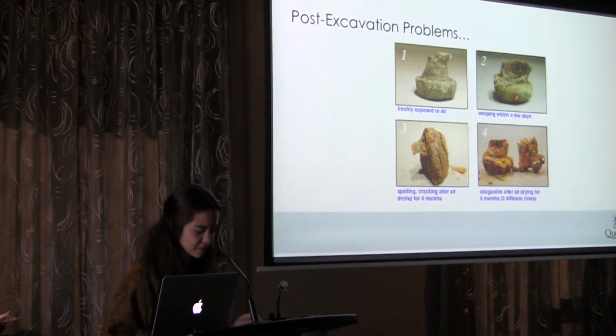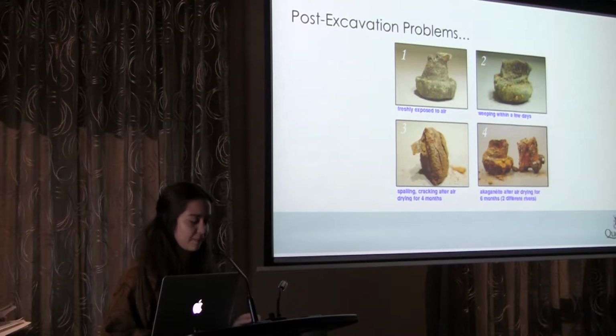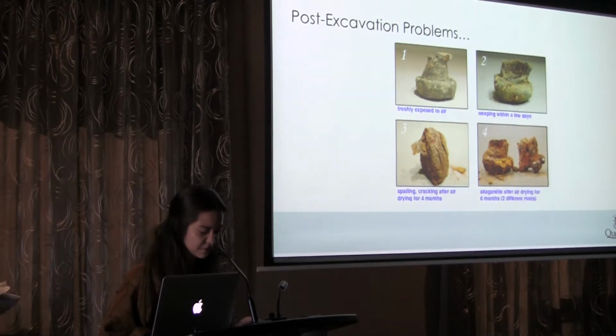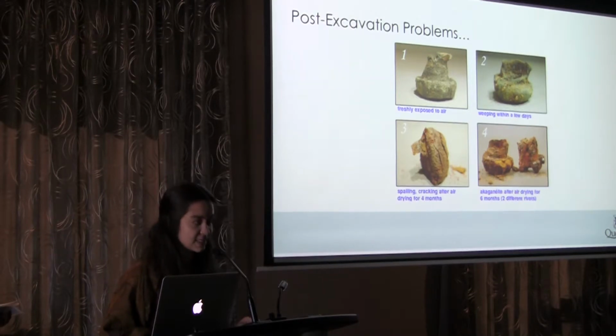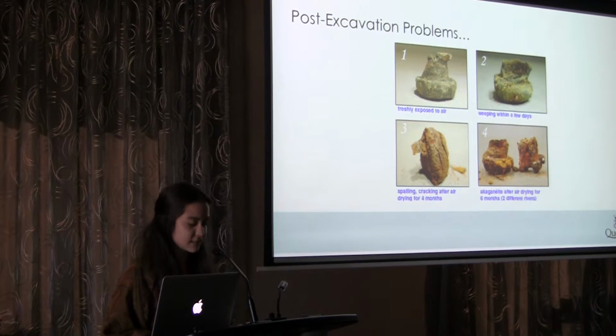Once objects are removed from the soil, they can start to deteriorate very rapidly. For example, this iron object was whole when it was excavated, but developed active and aggressive corrosion almost immediately afterwards. Six months later, without any conservation intervention, the artifact disintegrated and was effectively lost.